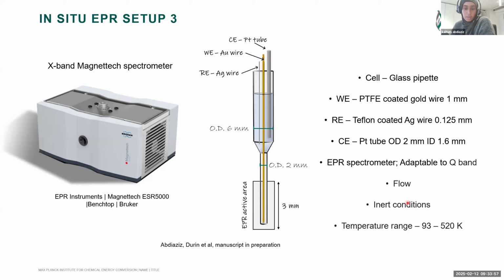In this setup, I'm able to adapt it to flow. All I do is have a connection here at the bottom, which is then connected to a peristaltic pump. With this setup, we are able to work at liquid nitrogen temperatures, but in our benchtop spectrometer, we can only go down to 93 Kelvin, and up to about 520 Kelvin, which is about 250 degrees Celsius. I have tested my setup from 93 Kelvin all the way to 100 degrees Celsius, but I have not gone higher, but the specification for the Magnettech allows you to do so.